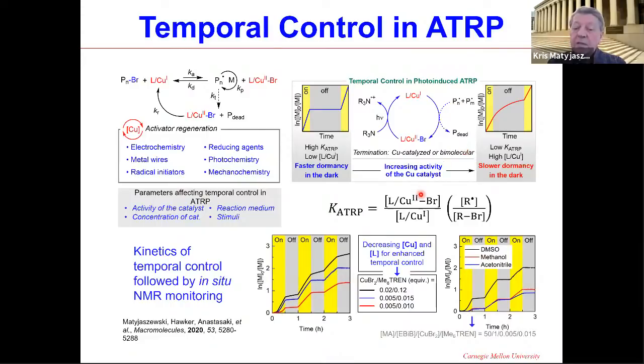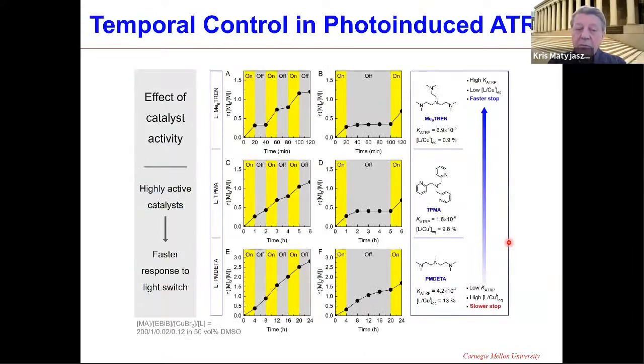So it depends essentially on how much copper 1 you have in this system, or what is the total amount of copper if you wish. So for example, in this graph, you could see if you use more and more copper and more ligand, the reaction is faster, and also this stopping is not as fast as it could be. In addition, you may have an effect of solvents, and you may also have an effect of the ligand or complex itself.